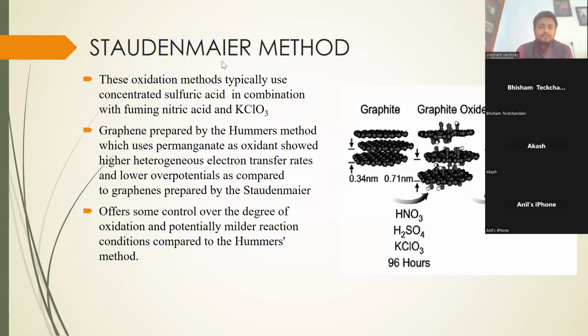Staudenmaier method. This uses KClO3 instead of NaClO3. The amount of oxidation generated from Staudenmaier is a little bit less, but it gives high control over the degree of oxidation. You can plan how much acid value or hydroxyl value you need from the graphene, which is important for some pH applications, because graphene oxide can have a pH down to 3. In aqueous solution, it can be highly acidic.